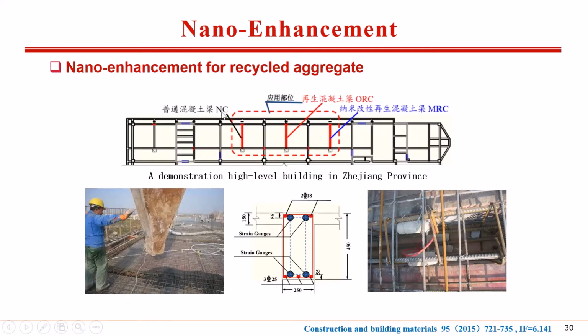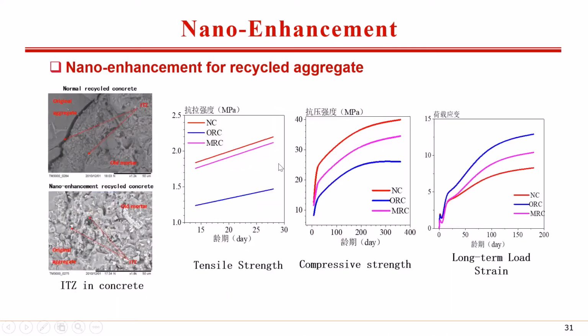We called them NC, ORC, and MRC. We can find the microstructure of interfacial transition zone. The tensile strength, compressive strength, and long-term load strength could be obviously improved by nano enhancement. It is truly a kind of efficient method for improving the properties of recycled concrete. Now we use nano enhancement in many areas. For example, the high strength recycled blocks, recycled concrete, and high performance marine recycled concrete, and so on.